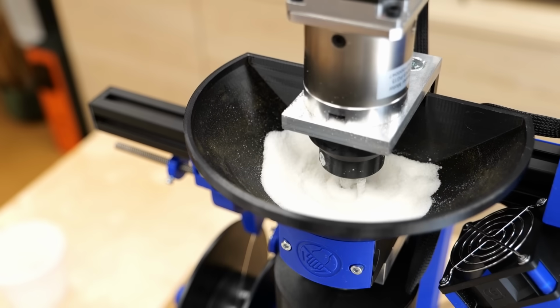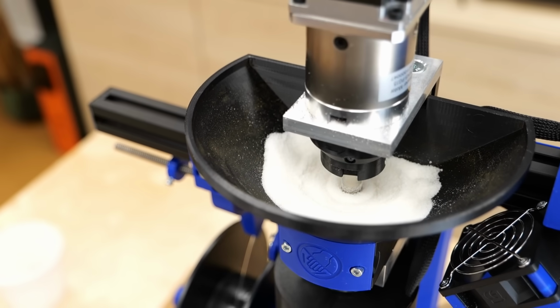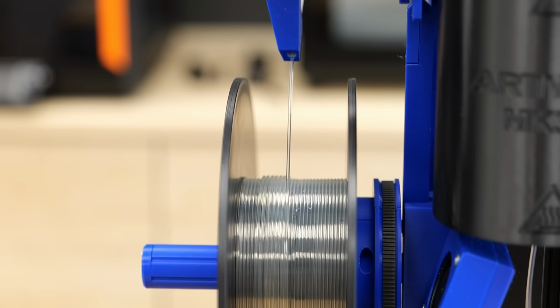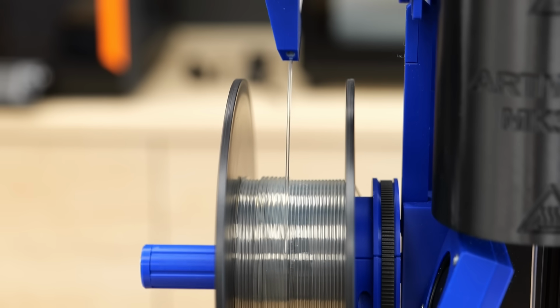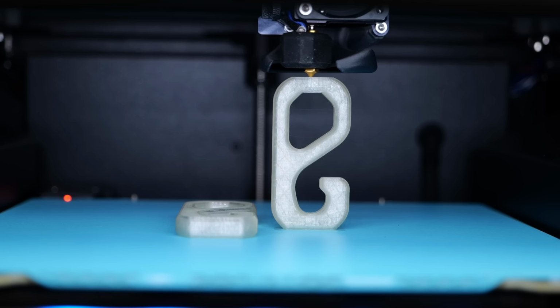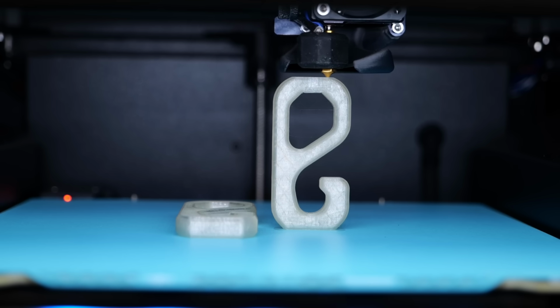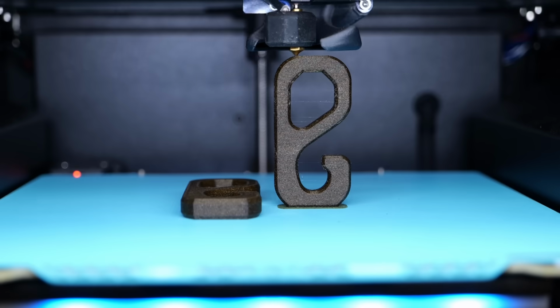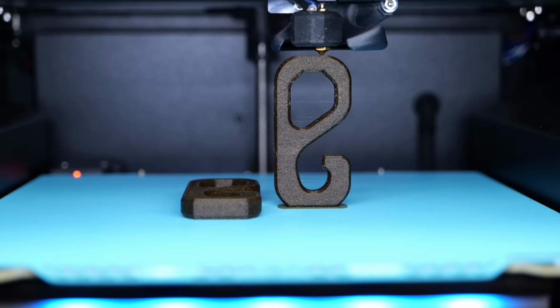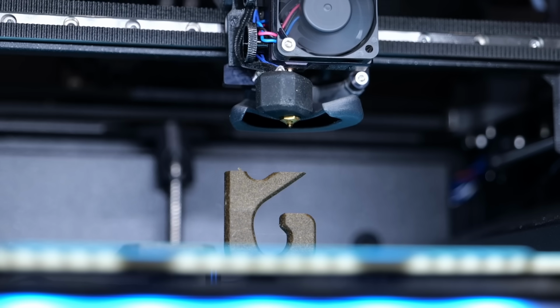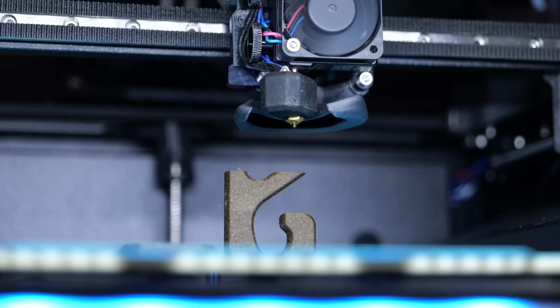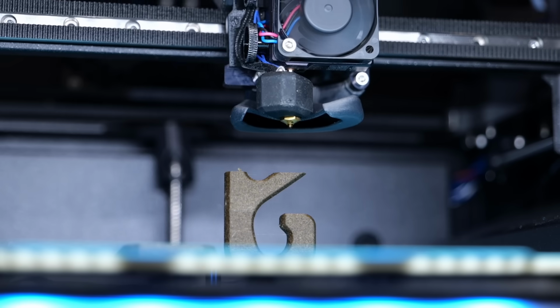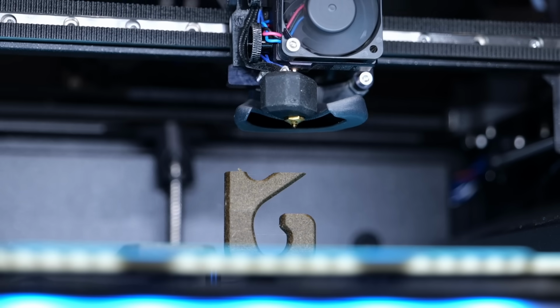For this, I first extruded some unfilled PLA from my PLA powder as a reference material so that we know how strong the parts would be without any fibers. Then I printed my good old test hook, once standing and once flat on the bed. That worked very well for the natural PLA, as well as the 5 and 10% variants. Unfortunately, I couldn't get the standing samples of the 15% and the 20% poop PLA to print, because the filament always jammed at some point.